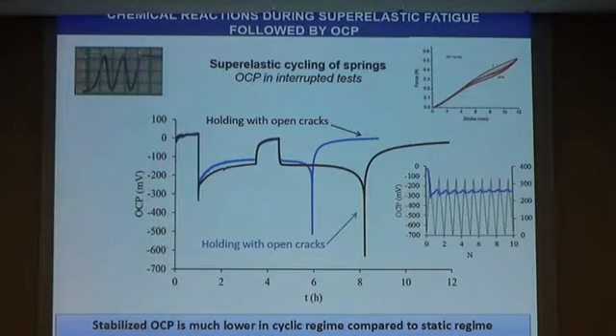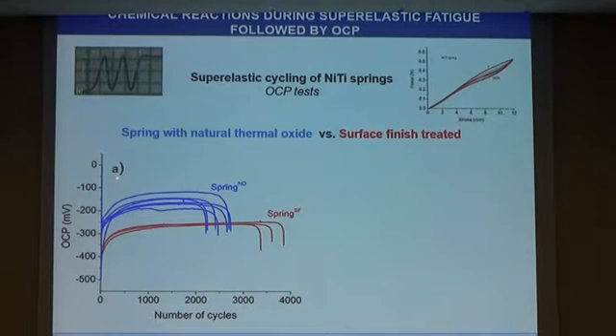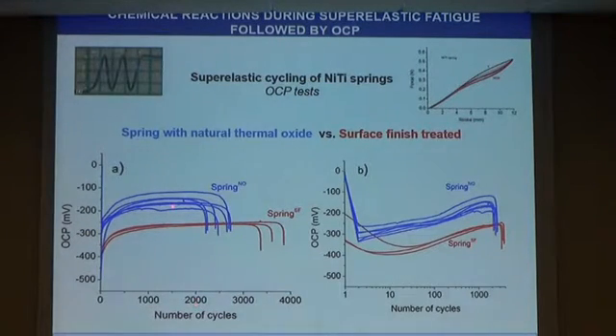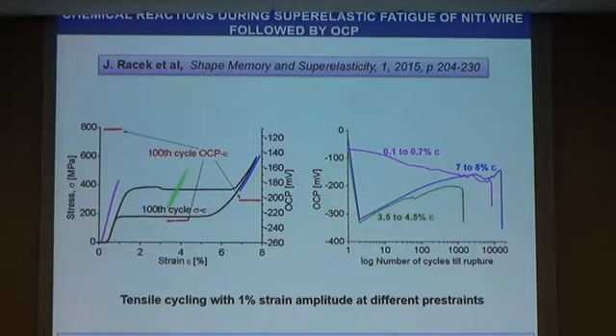If you do the same but stop at some moment, the chemistry immediately works and the original level of OCP will be recovered. But once you start to cycle, you come down. So this is evidence that in static and in dynamic regimes, the oxide works in a completely different way. It's a very good statistic. There are several springs with one type of oxide, and with a different type of oxide, the difference is about 1,000 cycles. Finally, all these break because of inclusions, but the statistic is still pretty good, so one can see the effect of the surface on fatigue performance, and my colleague Lukáš Kadeřávek will talk about this in more detail later. But I would like to go back to wires.